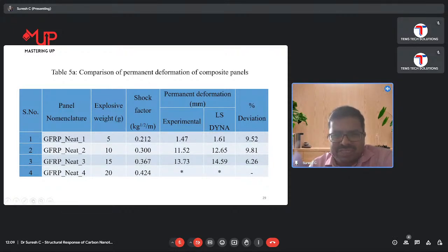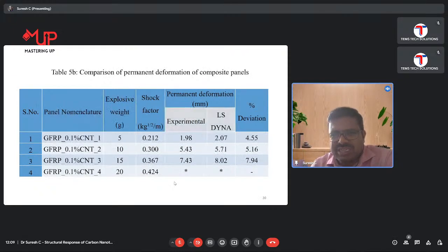And for 15 gram, experimentally the permanent deformation was 13.73, and from numerical it is 14.59, and the deviation is 6.26. As I told, for 20 grams, since all the edges are tearing, we are not able to measure it, both in experimental and in numerical.